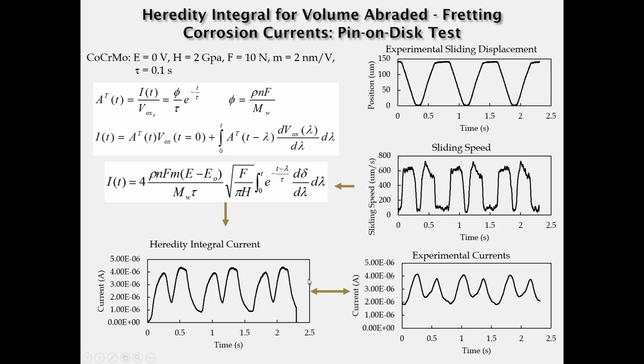And you'll notice the similarity both in terms of the magnitudes of the currents generated and the phase and the periodicity of the currents. All of it seems to line up very well. So we have a tool here that can essentially predict for us, using either set variables known from the literature or measured in the experiment, like the sliding speed, to make direct predictions of what we would expect from fretting corrosion.